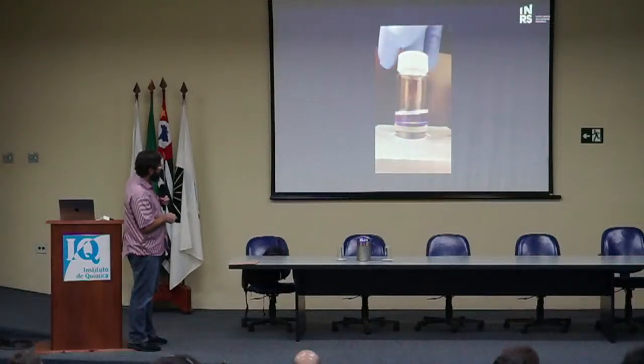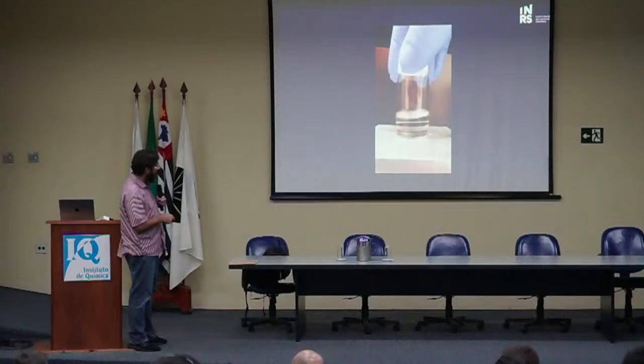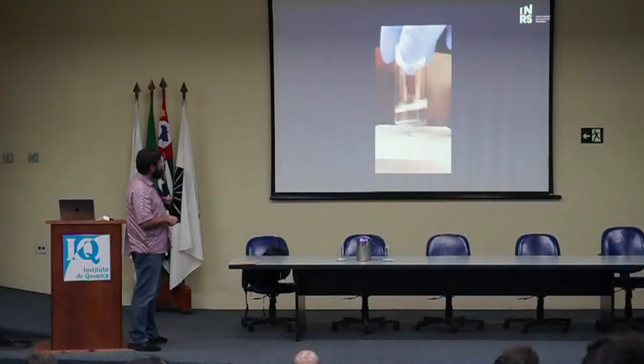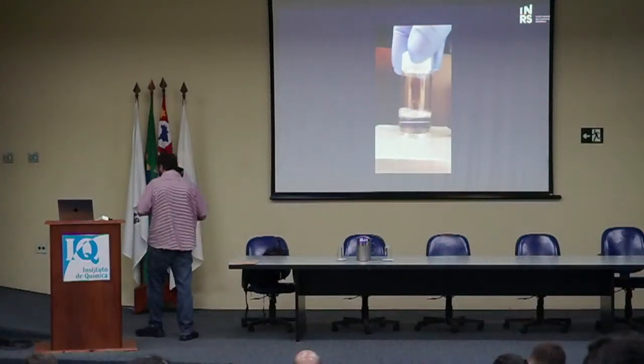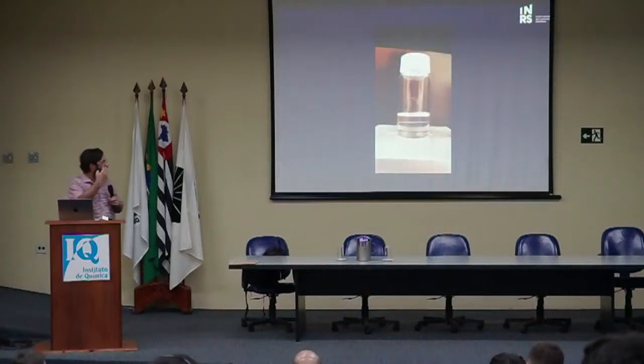This is what they look like in real life. You can see the near-infrared, you can't see the near-infrared laser, that's why we put the card. It's a 980 nanometer laser. These are nanoparticles in water. We have the blue emission from thulium ions, that green emission from erbium, and then we can mix and match to get other colors, depending, again, as I mentioned, on the concentration of the dopant, the co-dopant, and so forth. So we can get all the colors we want.